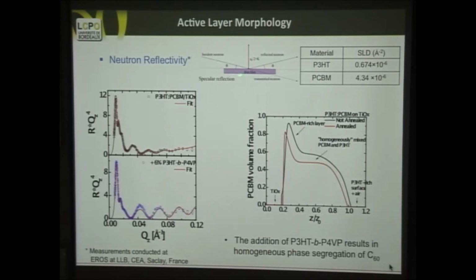So we did also neutron reflectivity to try to see what is the composition distribution of these two elements that we have there, the polythiophene and the C60 in the system. And these are the neutron reflectivity of the pure blend and the blend with the block of polymer. And what we see here, before annealing and after annealing, is that here you have the interface of titanium oxide, and you have the distribution of the C60 in the system, and you have the surface of the device, or otherwise said the anode of the device.